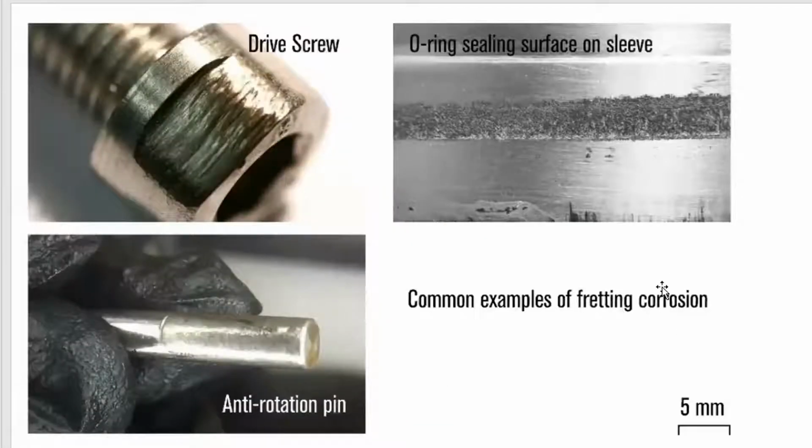And if you go back and look at this, this is interesting because this is actually the low pressure side of the O-ring. And so what happens is here you get a very definite line, and that's because that's where the extrusion gap is. Back up here, you can see this is kind of messy because that's where that O-ring is lifting and closing, lifting and closing. And so what's happened is this corrosion probably started up here. Let me zoom in a little bit.